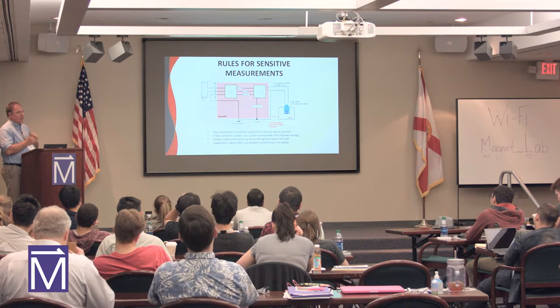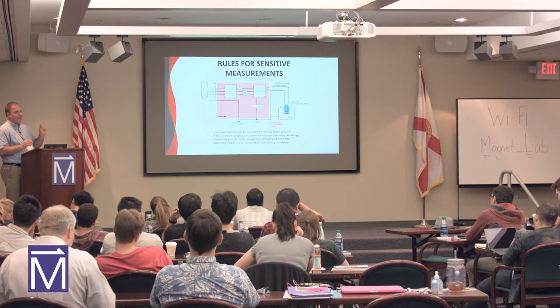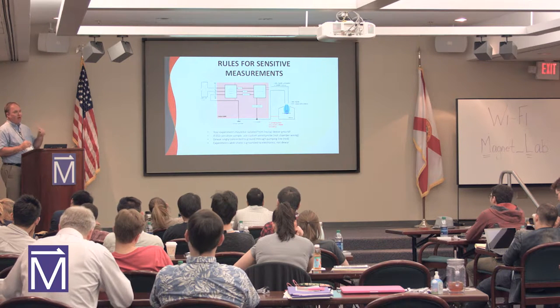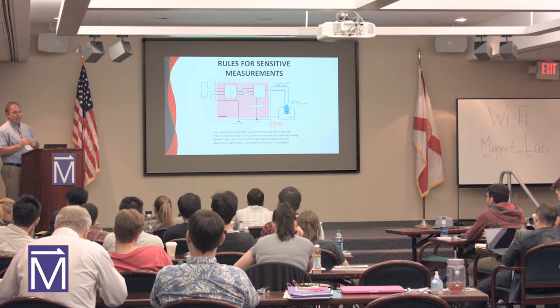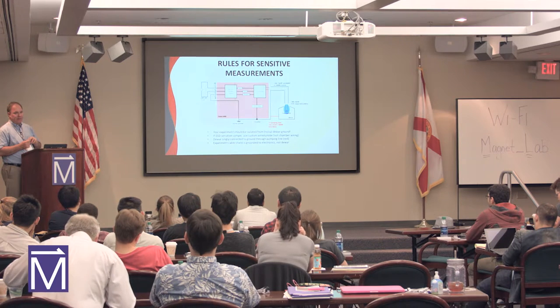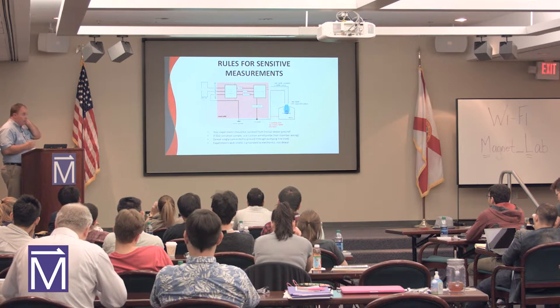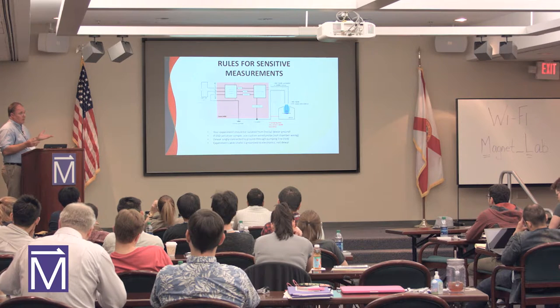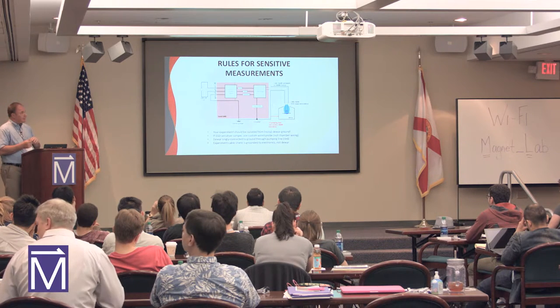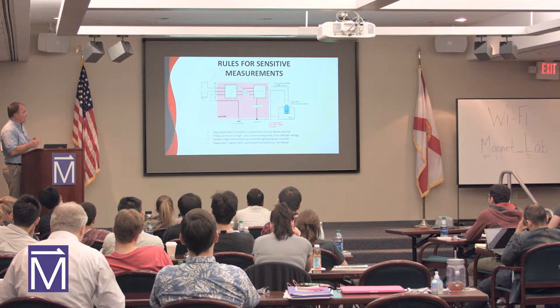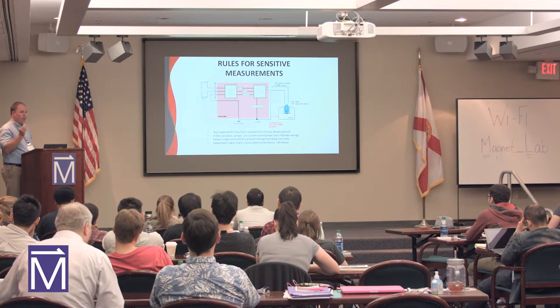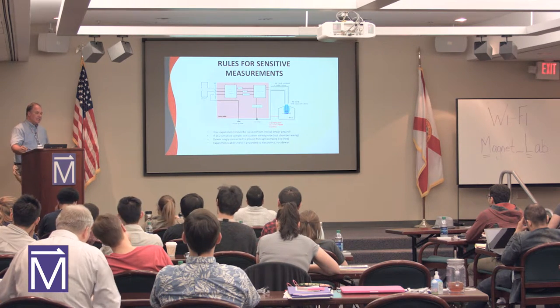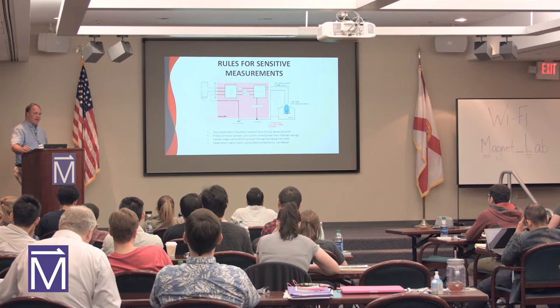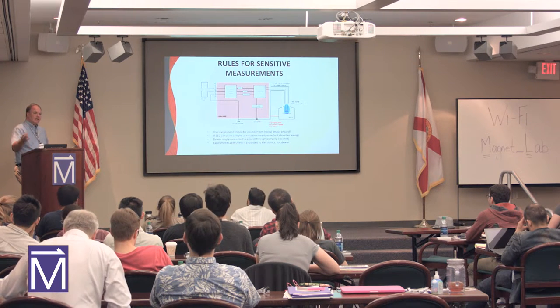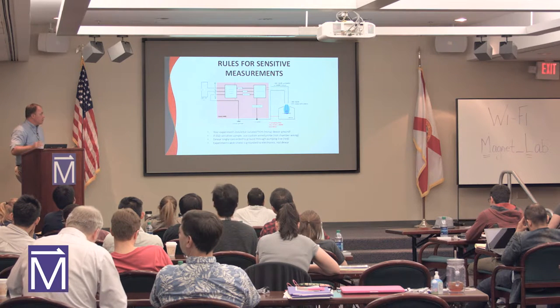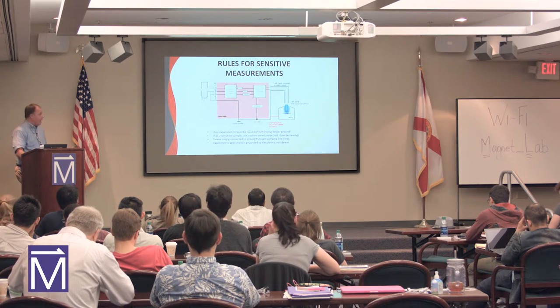ESD sensitive sample. So here's the case where everything that I've talked to you about the pucks goes out the window. You need to make your own probe and run your own wires down to the probe if you have those samples. And it's due to the way that the ground in the system is. So you have to take care of this case. When we have customers that have ESD sensitive samples, we recommend that they design their own type of probe for that. We have some solutions for that, and we have some solutions coming up.